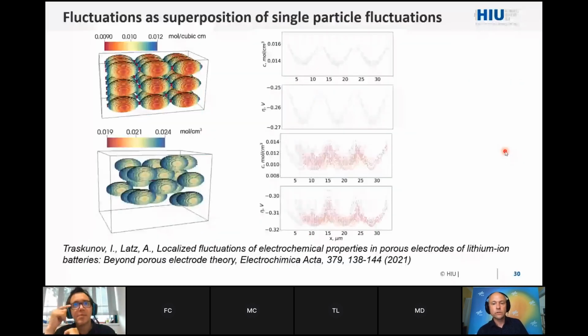And here to show that these fluctuations, this very random looking fluctuation, are really due to the fluctuations which we observe on particle scale. So Igor did this very artificial regular configuration here, where you see fluctuations of the concentration, fluctuations of the overpotential, which are of course in the same oscillatory way which you have here.